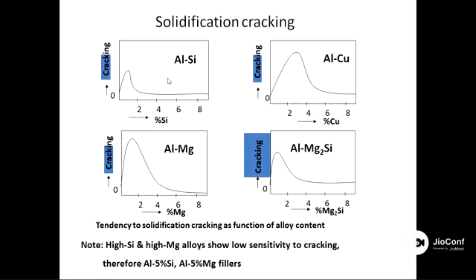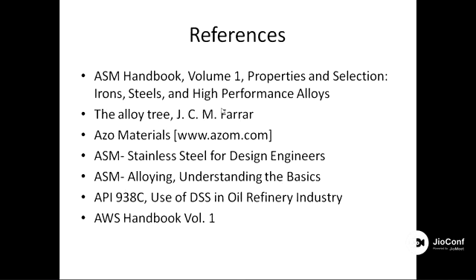So you should use a filler metal having more than 2 percent, practically 4 percent silicon. Likewise, use magnesium with more than 6 percent. So Al-5Si and Al-5 magnesium fillers are used. They can be used for welding of aluminum alloys.